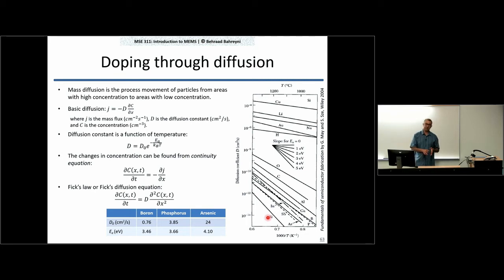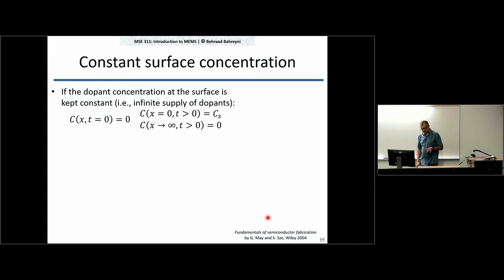Now, we have a partial differential equation that we can solve under different conditions. You are not required to solve this equation, so don't be, let's say, scared of what we have here in front of us. What we are going to look at is two special cases where we actually utilize this equation to do our diffusion, to do our doping. In the first situation, let's assume that we have a constant surface concentration of dopants, meaning that, let's say, you have your wafer inside a furnace, the temperature is high enough, 900 degrees, 1000 degrees Celsius, and I bring a flow of phosphorus atoms constantly to this surface. I make sure that there is an infinite supply of phosphorus that is coming in and keeping the concentration of phosphorus at the surface of silicon constant.